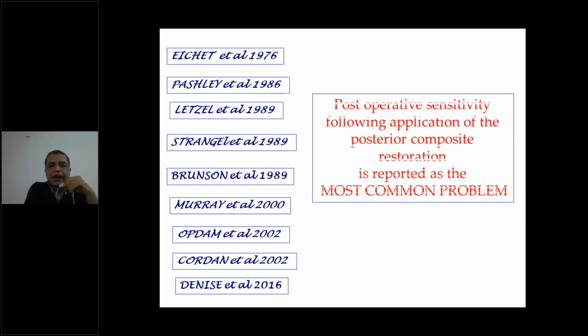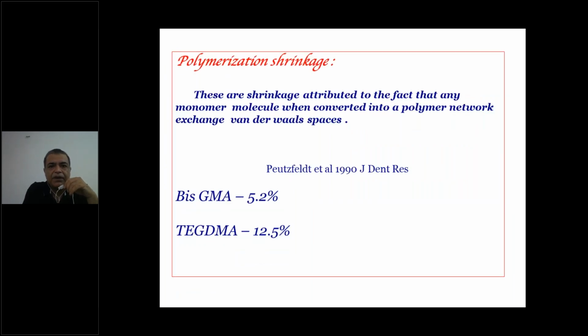So the most common problem with composites is post-operative sensitivity. Now, why does this post-operative sensitivity happen? It does not happen because we are etching a tooth, okay, because that is what people used to think earlier, but it is not that. The reason basically is the polymerization shrinkage and not the etching of dentine. Any resin will shrink, as I have shown you in the last video also.